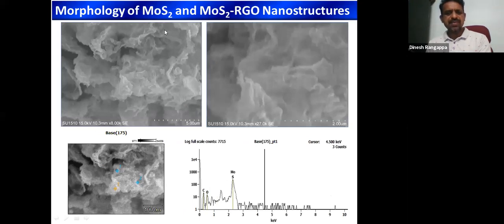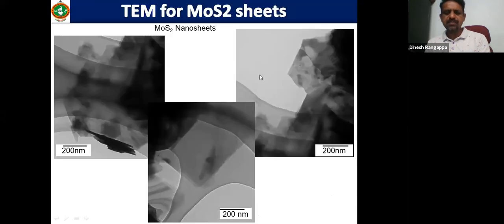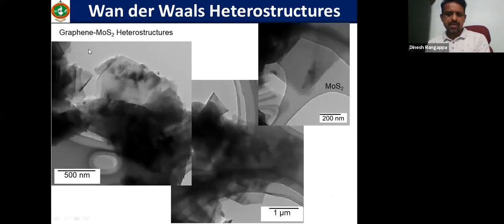This molybdenum disulfide we mixed with RGO and synthesized a molybdenum disulfide and RGO nanocomposite. You can see the morphology difference, only molybdenum disulfide and RGO and molybdenum disulfide here. So this is a TEM image of molybdenum disulfide, and a TEM image of the graphene and molybdenum disulfide heterostructure. You can see the molybdenum disulfide is coated on the graphene sheet.